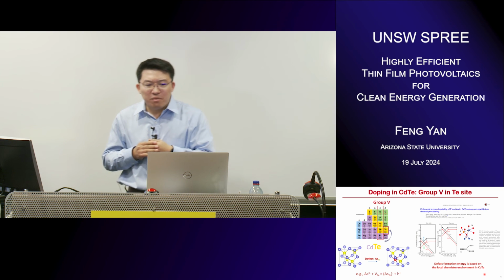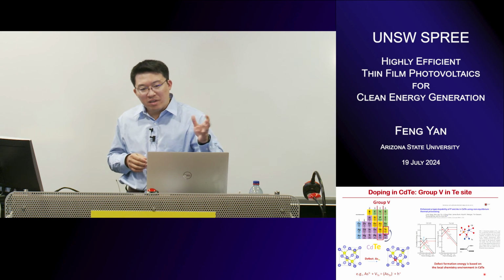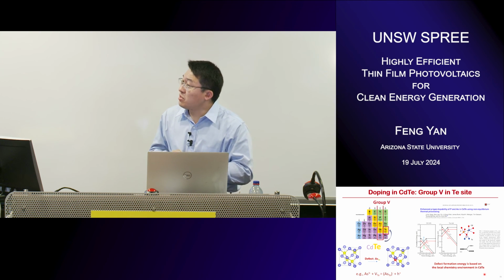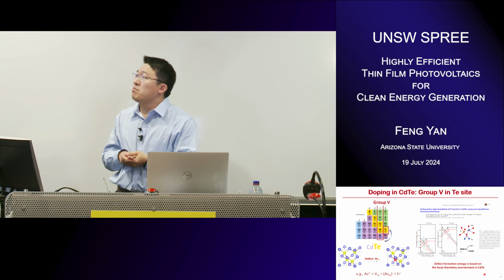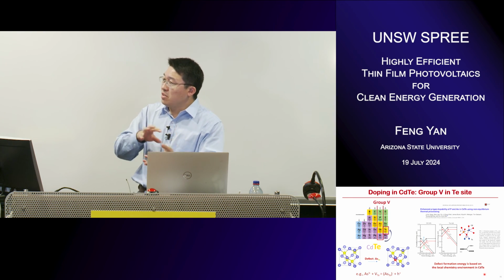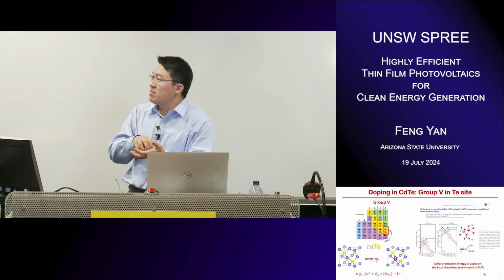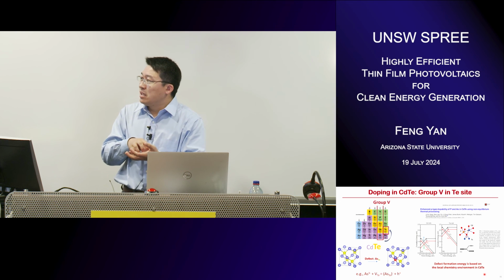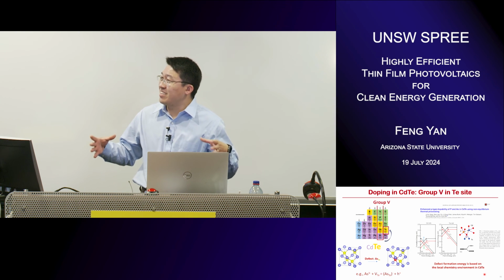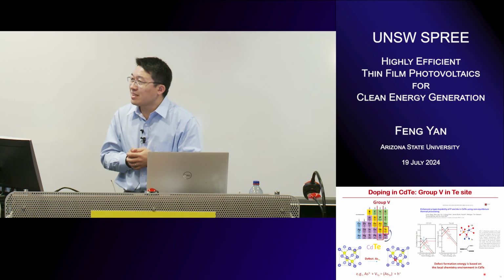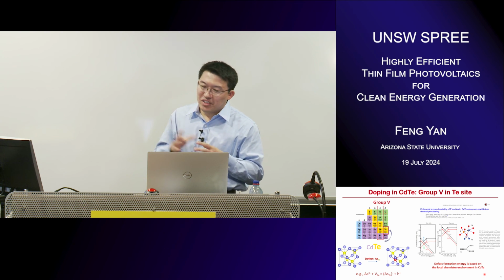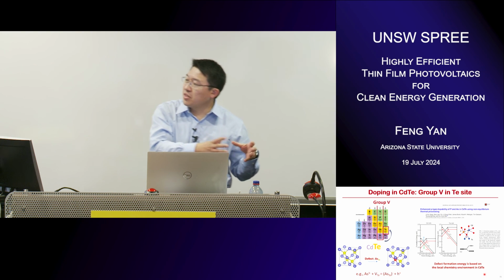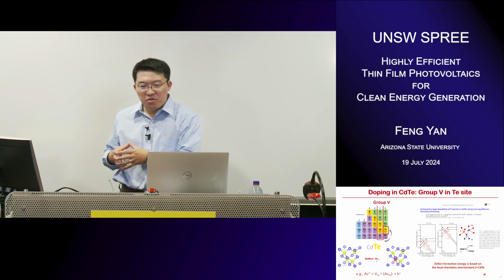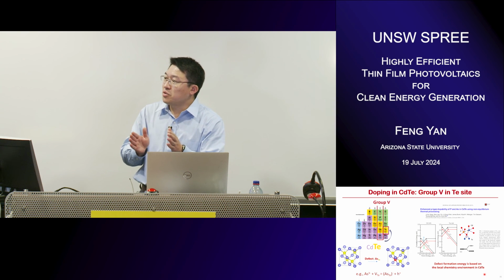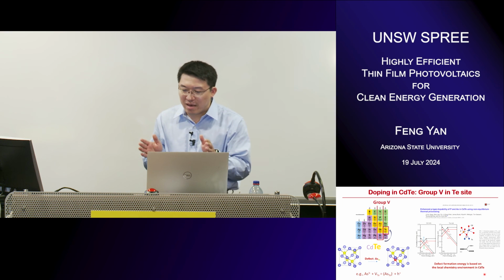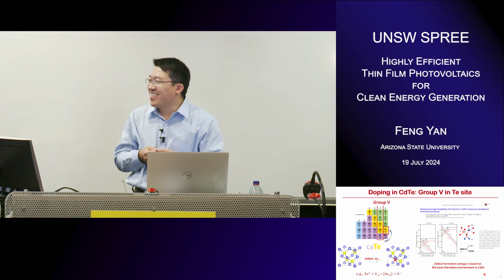So that's why we have a researcher trying to grow single crystal cadmium telluride using MBE. It's ongoing, to see how this treatment impacts the grain interior. If we can grow a single crystal, then we can imagine a bigger grain interior, right? You mentioned the VOC improvement. Yes, the single crystal. One of the challenges is how to transfer the learning from single crystal to polycrystalline. It's a huge challenge because there is a big gap, but we are working on that to fill it.